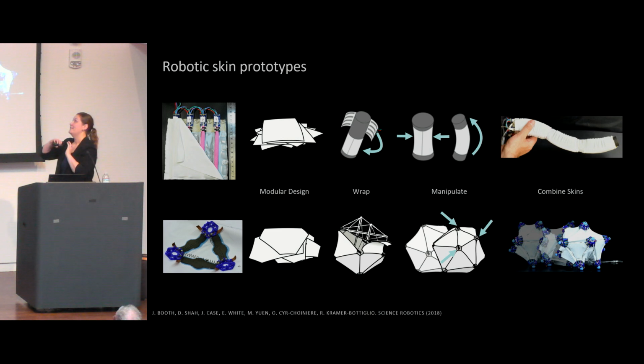We can layer them. Now, the one thing that we had a lot of challenges with, so we have this idea that robotic skins will be these incredibly planar skin-like membranes, right? But you can see based on the components that we've chosen that they're a bit bulkier than that. And as you start layering them up, they do accumulate bulk, and it impacts the mechanics of the system a lot. The other thing is, as we're attaching these skins to a body, we have to have very good adhesion between the skins and the body for that force to actually impart to the body, right? So a lot of times we'll see if we have imperfect adhesion, if they're not perfectly connected, then some of the force is lost through slipping around the surface. And as we accumulate skins on top of one another, that problem becomes exacerbated. The force that we're trying to apply might be very far from the body that we're trying to apply it to.